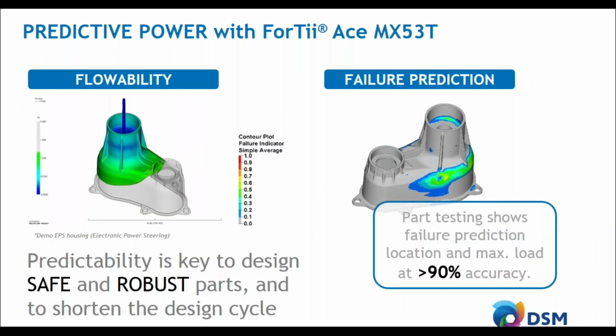Of course, before reaching that stage, you have to do a flowability analysis, look where the weld lines of your part are, to see that they are not in critical areas where you have high stress concentrations, so we are able to optimize the design. And then, of course, we go into the failure prediction and then compare it to testing. At this moment, we are able to do that with 90% accuracy.